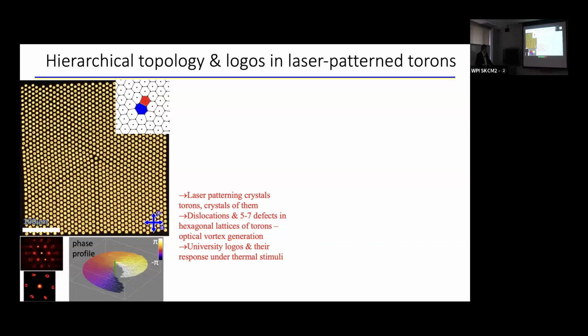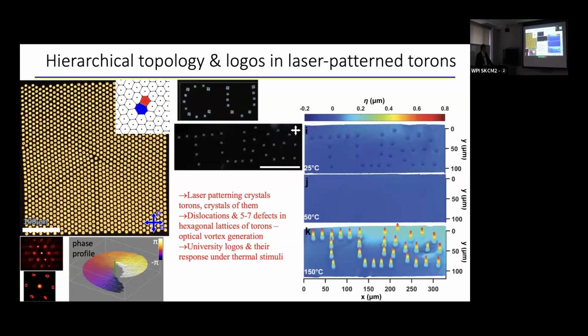So a phase singularity in light that you can see in here, and also in a diffraction pattern from this type of diffraction grating, where for every single first order beam, you can see a hole which is a bit small, right? Because these are the elementary charge vortices. And then in the second order, you see bigger holes, and these are already the Q equal 2 charge vortices and so on. Now, importantly, this example in here shows just the phase profile for one of these optical vortices generated this way. But what we were interested in was to control these torons in such polymerizable material so that we can then control the surface topography at will.